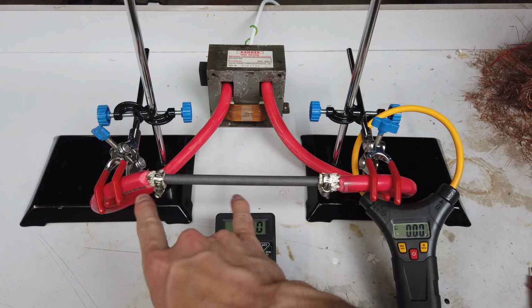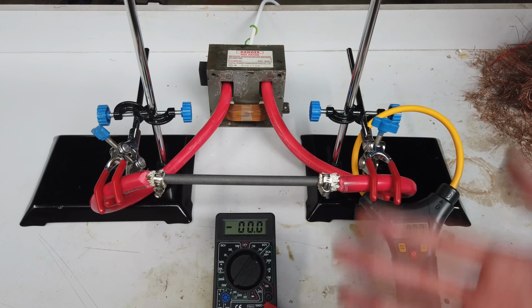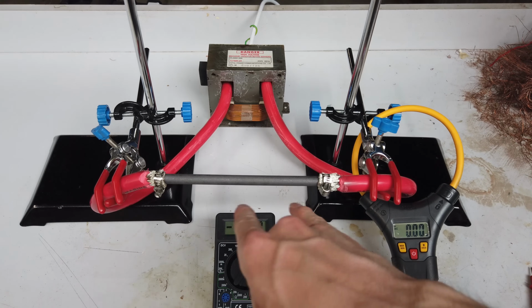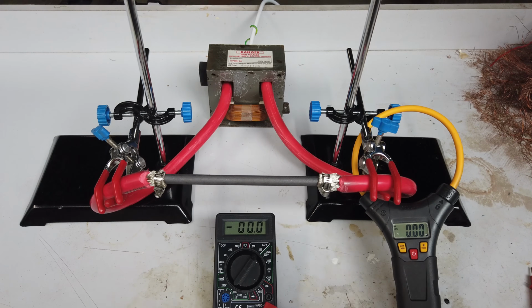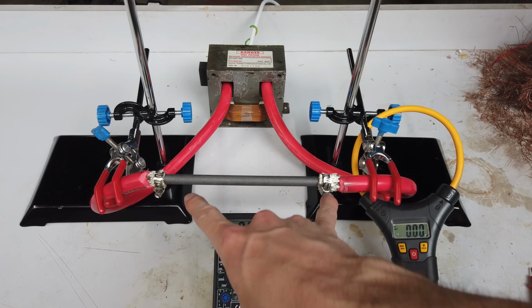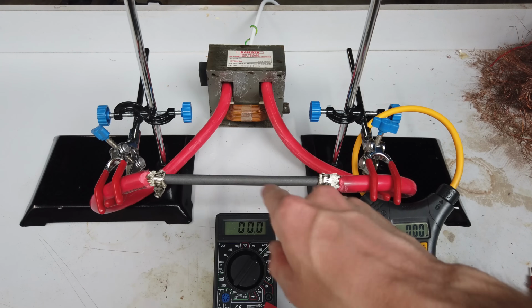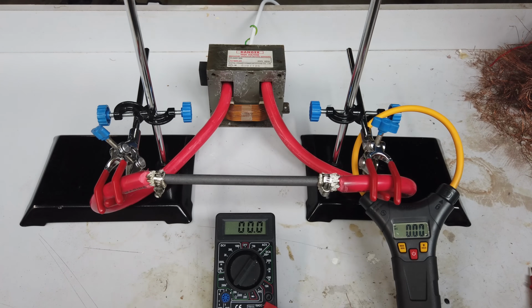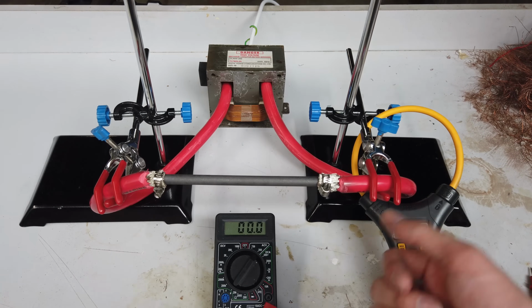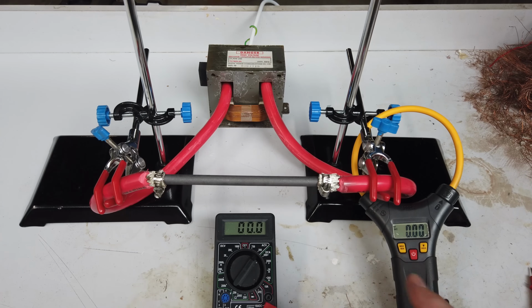Number one is we can shorten the length of the graphite that we're heating up. This will do two things. It will decrease the resistance that we're applying the voltage over, and also decrease the amount of graphite that we need to heat with the certain amount of power that we're running. So say if I decrease the length of this graphite by a factor of 3, just take a third of this length, we should be able to get a third of the resistance and then 3 times the power. Per gram of graphite, we're getting 9 times the power. That's in theory anyway.